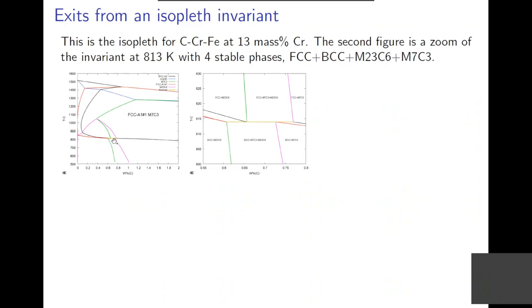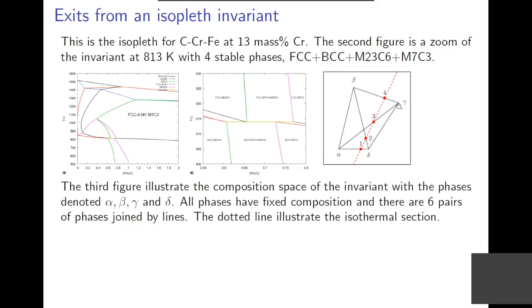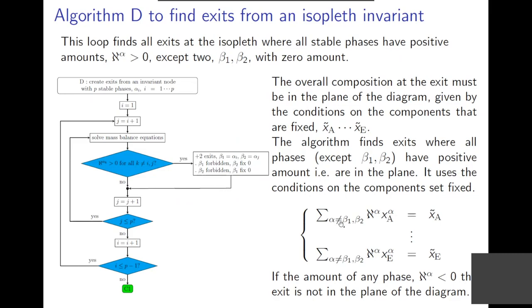And to find out which exits you have in the plane of the diagram, one can make a figure like this one, because these are the four phases which are stable at the invariant. And this dashed line means the plane of the calculation; this was for 13% chromium. If you had 15 or another fraction, you would have different lines here. But the crossing of this line with the combination of two sets of phases here determines the exits you have. So here we have four exits. And at each exit, you have two lines meeting. So the algorithm here determines where you have the correct mass balance for your isothermals, for your isopleth calculation. And those are the prescribed compositions of your isopleth.